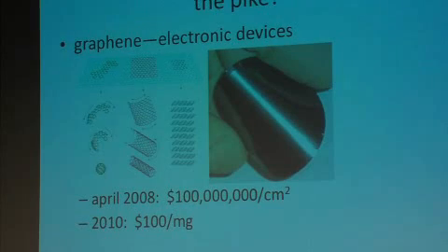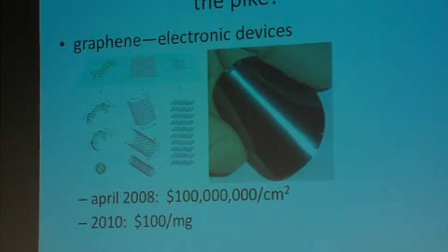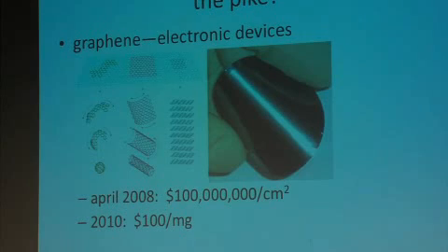And those have just fabulous mechanical and electronic properties. There's been kind of a graphene gold rush in the last couple of years. This image here is showing not, unfortunately, a single sheet of graphene. This is actually graphene paper, which is made by filtering a suspension of mostly graphene monolayers. You just filter it on a piece of filter paper, and then you can peel off this composite sheet of graphene. High conductivity, flexible substrate with potential electronics applications.